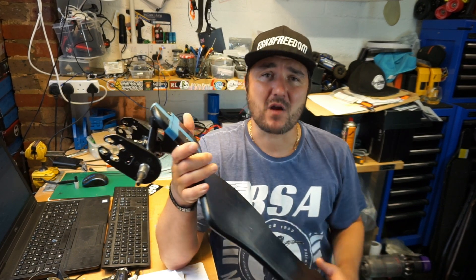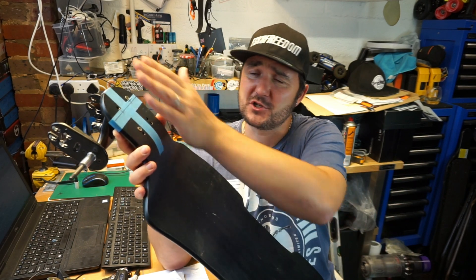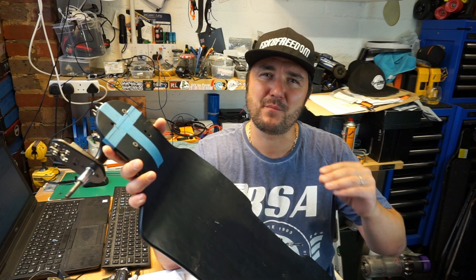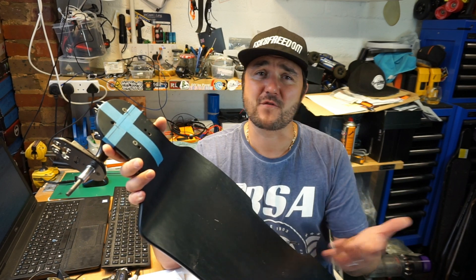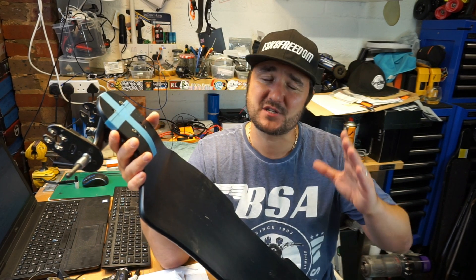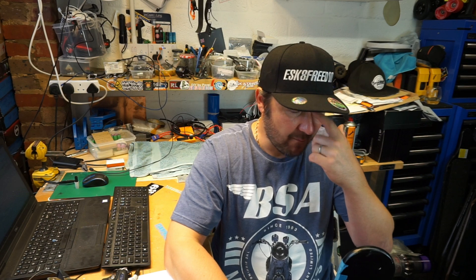So I confidently got myself another one and put two skins of carbon fiber to reduce the flex. To summarize: I'm 110 kilos, so I'm quite heavy. A single layer on the top will reduce the flex by about 10 to 12 percent. Top and bottom singles will reduce the flex about 50 percent — a lot. So on the Beast I kind of would have preferred just a bit more flex, but the strength is really really good. With dual carbon on the top and nothing at the bottom, flex reduces by about 30 percent — that was absolutely perfect for the Tsunami. Unfortunately I can't get these decks anymore, which is another problem.